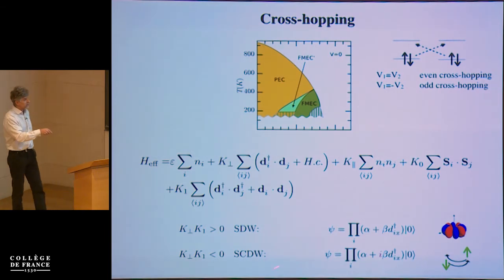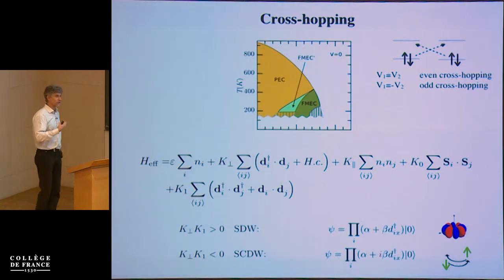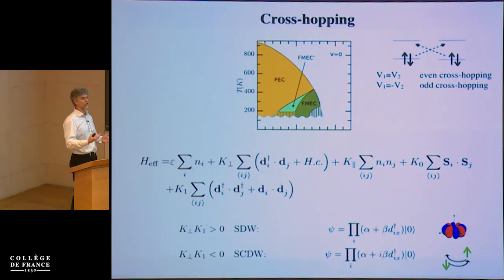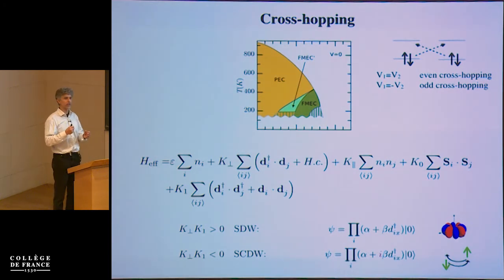If you're in this phase where the order parameter is purely imaginary, you can show that the ordered state does not break time reversal symmetry, and it can be described as a pattern of spin currents that are flowing within the atoms or also on the lattice.